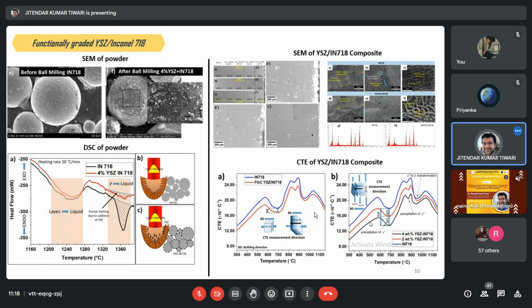So what kind of phenomena? The first one is what we call precipitation. This particular phenomenon is happening due to the precipitation of gamma prime. Gamma prime is basically an FCC structure, and it generally forms in nickel based superalloys, due to the combination of nickel and aluminium. So the formula is Ni3Al, and this is an ordered structure. The aluminium sits at the corner positions, and nickel sits at the face centered positions. So that's how the FCC contributes. Nickel will contribute 3 atoms, and aluminium will contribute 1 atom. So Ni3Al is the stoichiometry of the gamma prime.